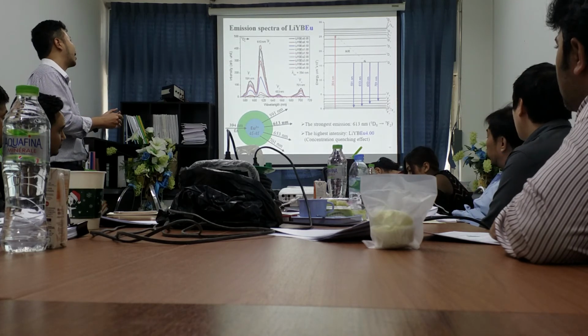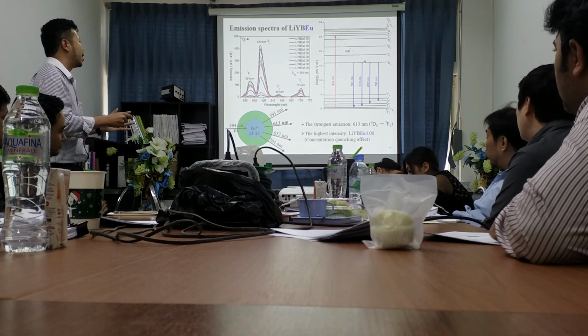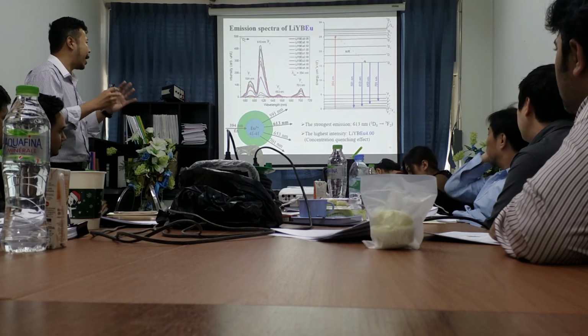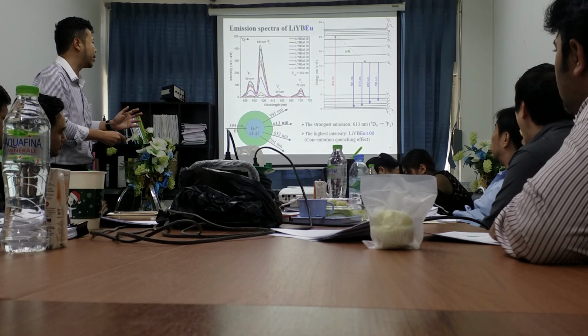We found for emission, the strongest emission is located at 613 nanometers. This transition comes from the luminescence level 5D0. The emission intensity is highest for the 4% Eu glass. This comes from the concentration quenching effect.